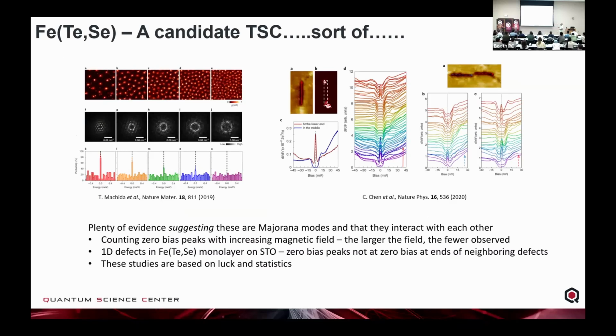where if you put it in a vortex, or put it in a magnetic field to create a vortex, you should generate the zero bias peak inside the vortex. And if you increase the magnetic field and have more vortices, you see fewer and fewer of these things, indicative of the interaction of these Majorana modes.